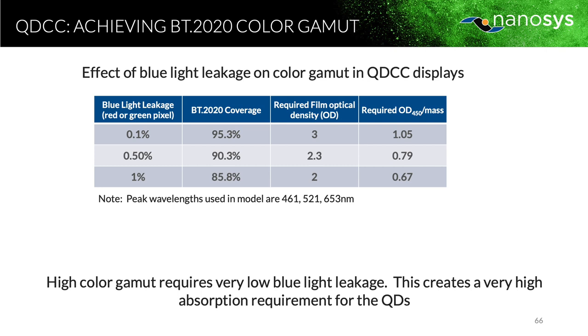So I'm going to walk you through this slide a little slowly. If we focus on the first two columns initially, we're looking at blue light leakage here. This is the amount of blue light that's leaking through that thin layer of quantum dots. So if it's 1% blue light leakage, think of it as 99% blue light is absorbed. Okay, you're absorbing almost all blue light, and presumably that's getting converted into the desired color. Well, if you have 1% blue light leakage, you can see that you have about 86% BT2020 gamut coverage. If you have about a half percent, it goes up to 90. If you have 0.1%, meaning you're absorbing 99.9% of the blue light, you have about 95%.